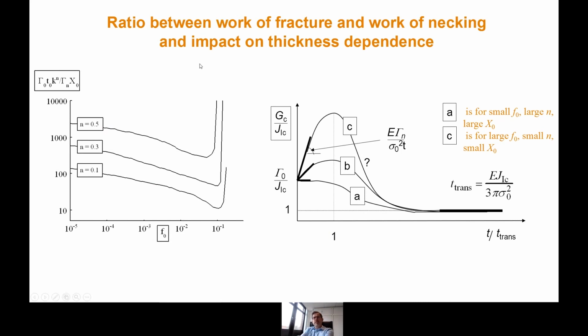But the final message in the paper was the following. We tried to predict the ratio of gamma zero over gamma n, and there are some normalizing factors there which make the result quite general. Basically what you see on the curve here, I will not describe the details, is that the ratio between gamma zero and gamma n with these normalization parameters can get basically any value depending on the porosity in the material, the strain hardening exponent, etc. So basically you can have everything.